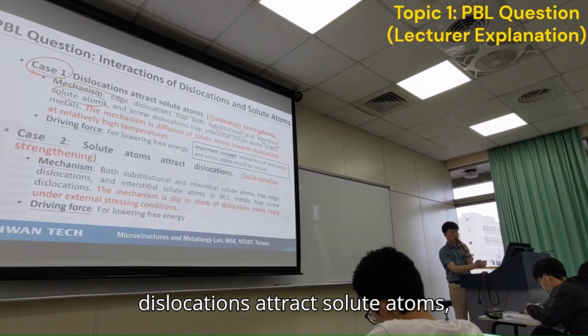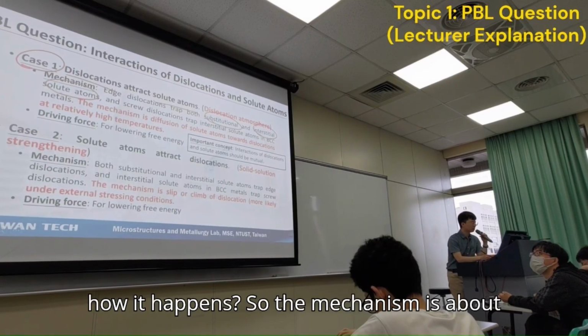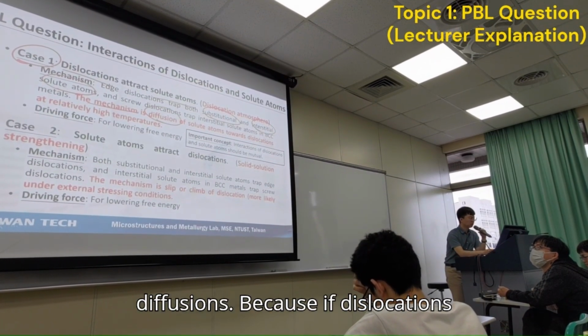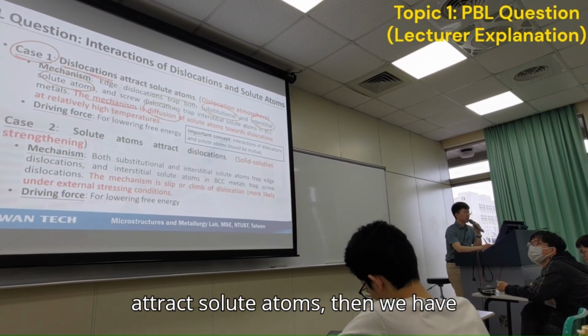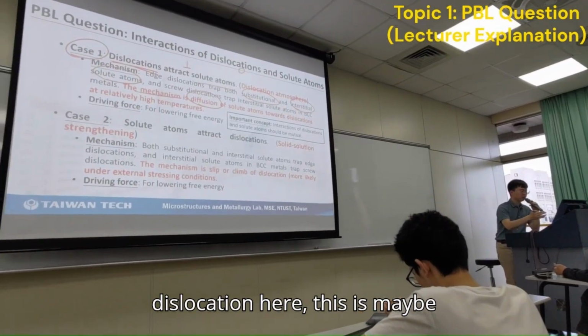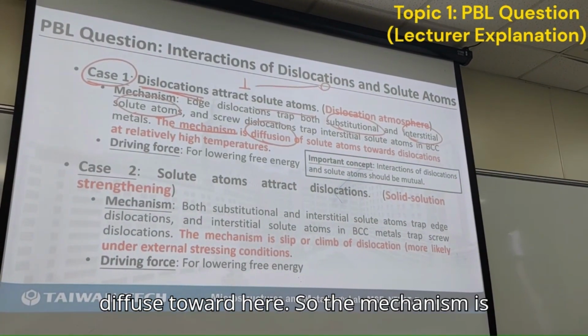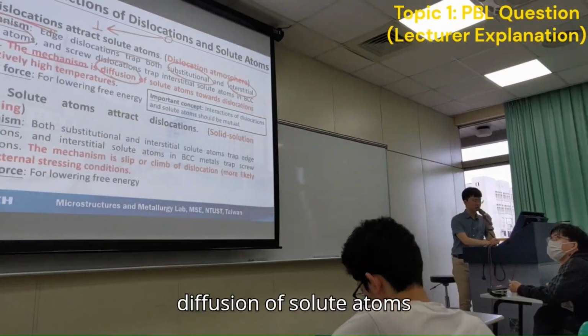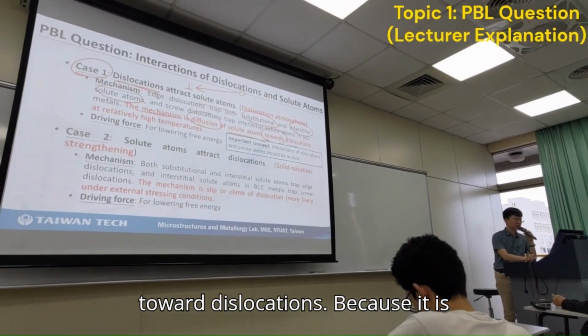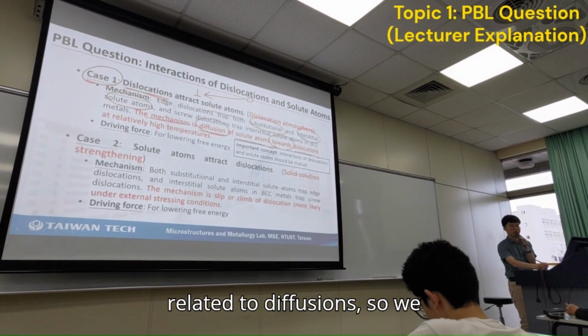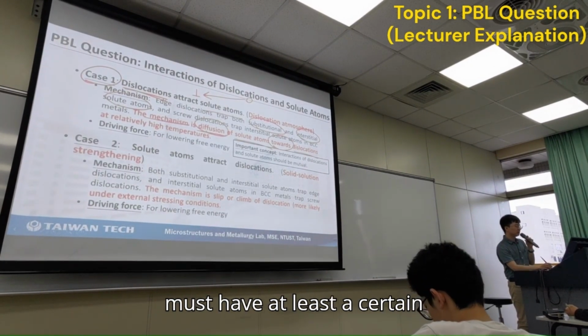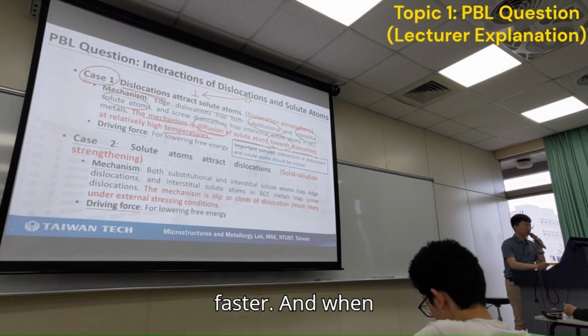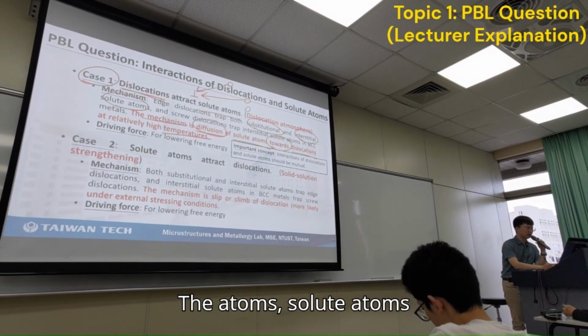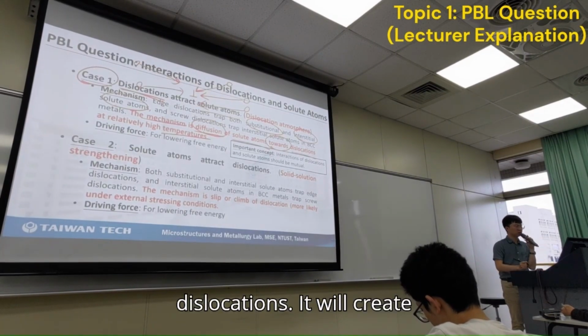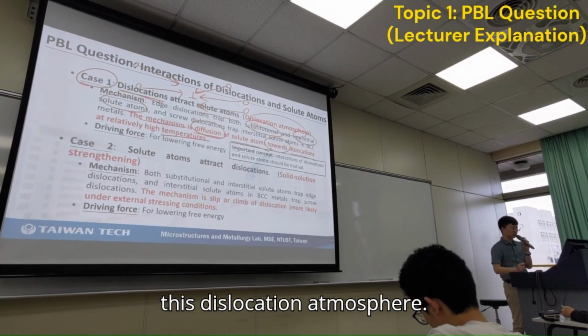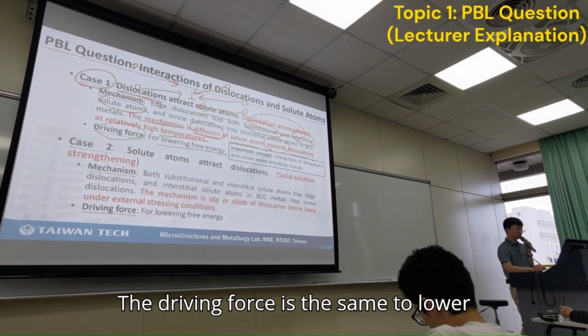And when dislocations attract solute atoms, how does it happen? The mechanism is diffusion, because if dislocations attract solute atoms, then we have a dislocation here and maybe solute atoms nearby. They must diffuse toward here. So the mechanism is diffusion of solute atoms toward dislocations. Because it is related to diffusion, we must have at least a certain temperature so that atoms will diffuse faster. And when the solute atoms diffuse toward these dislocations, it will create this dislocation atmosphere. The driving force is the same, to lower the free energy.